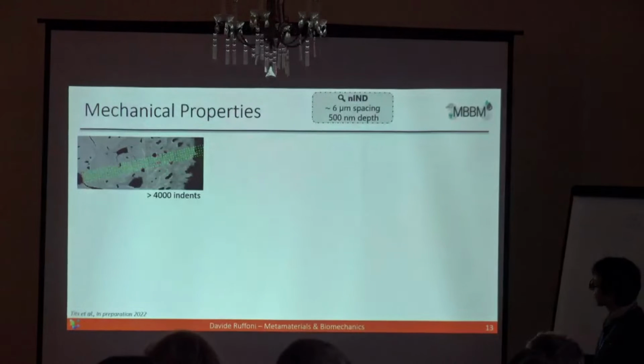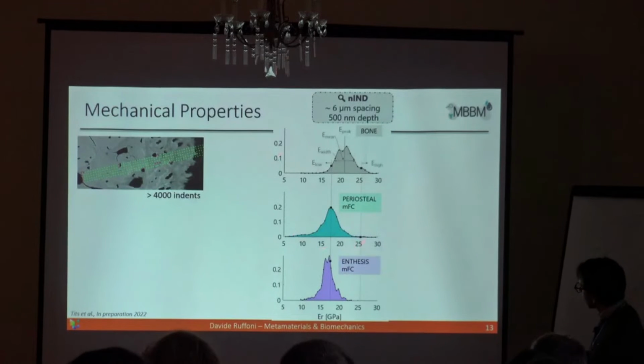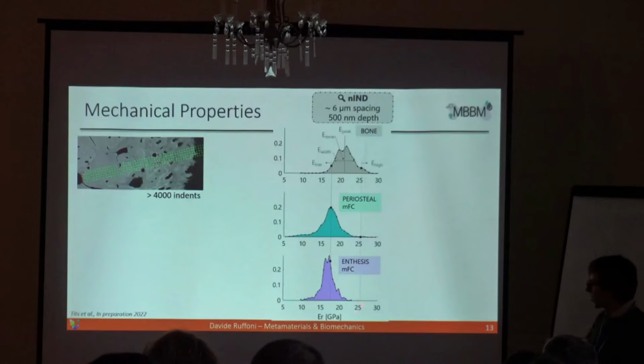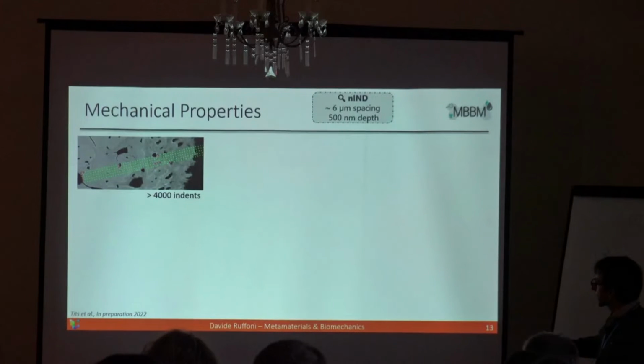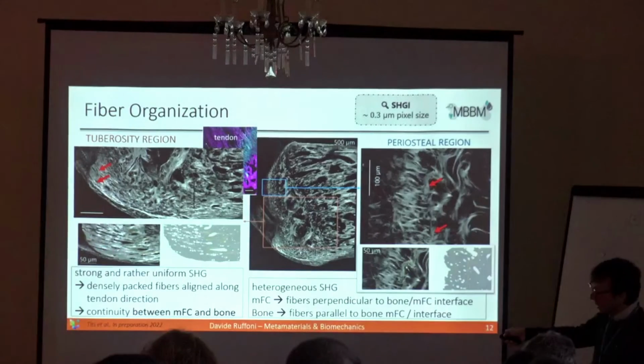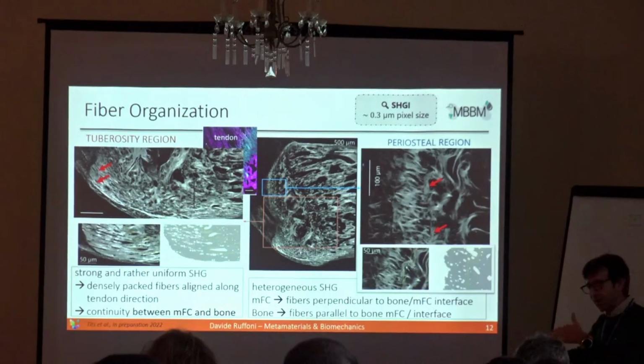Then we did some nanoindentation. We did several grids, and with nanoindentation we measure the local elastic properties of the tissue. What we see is that enthesis fibrocartilage, which is the fibrocartilage attaching tendon to bone, is much more mechanically homogeneous. These are frequency distributions of the Young modulus that we measured in bone, in periosteal fibrocartilage, and in enthesis fibrocartilage. At the attachment side, we see much more homogeneous mechanical properties, which somehow reflects the fact that fibers are also much more organized and oriented.